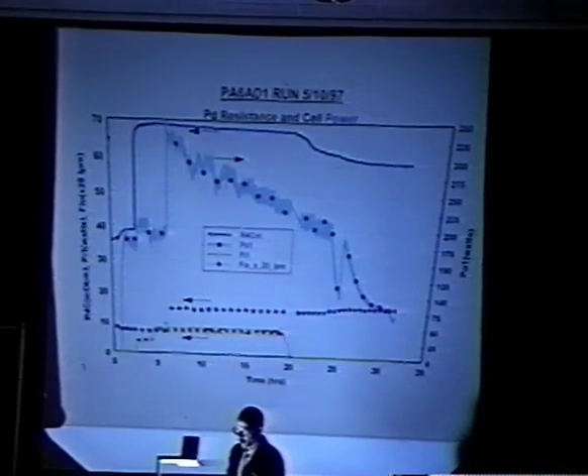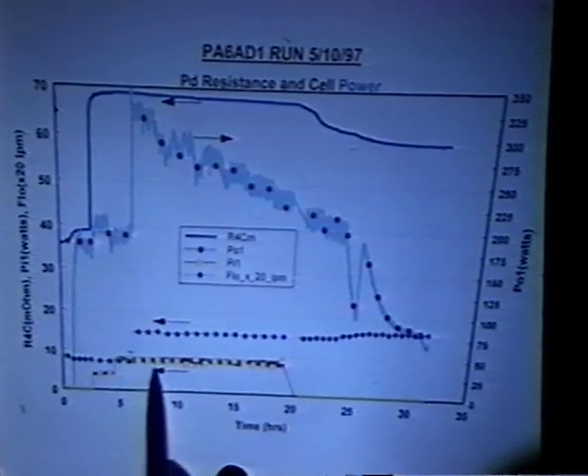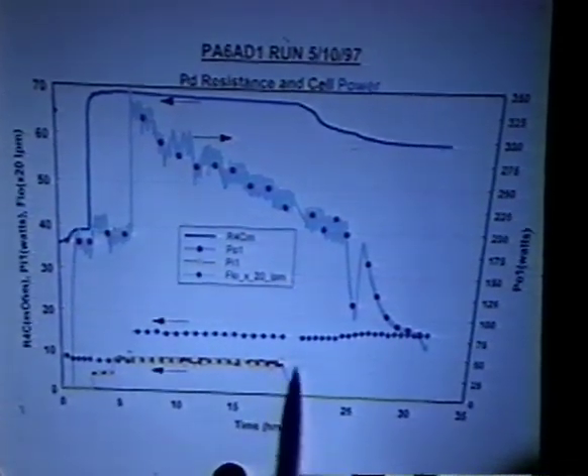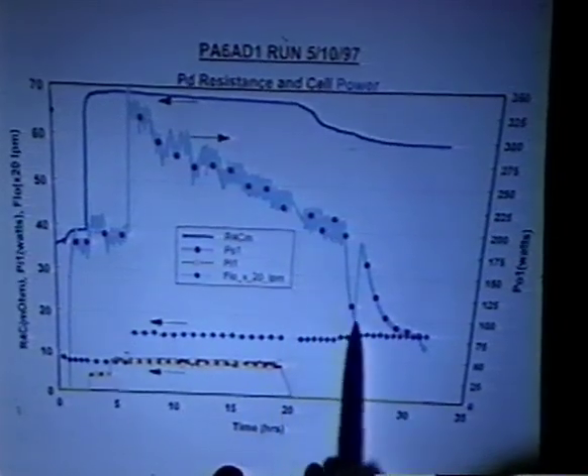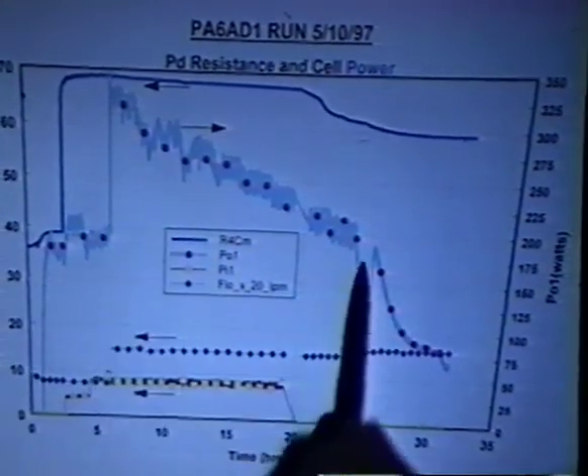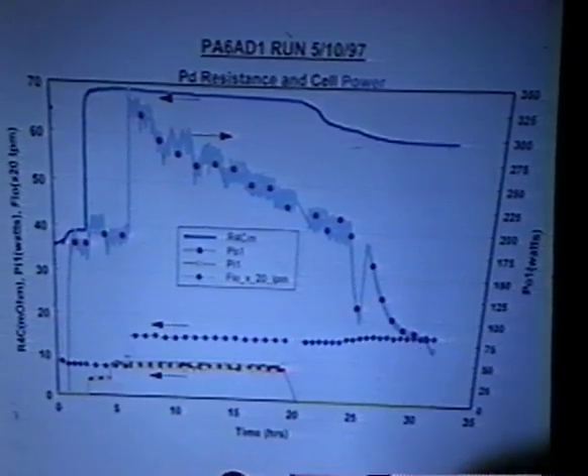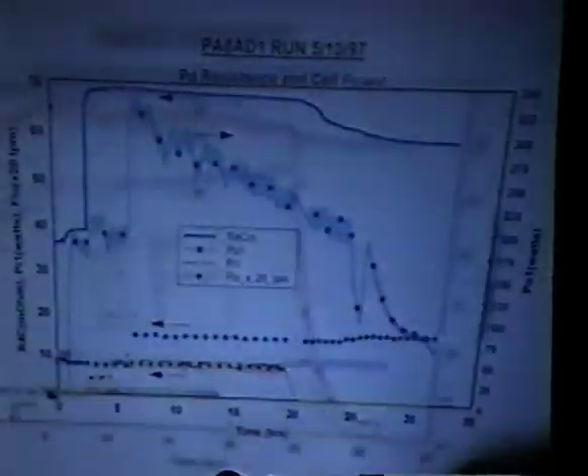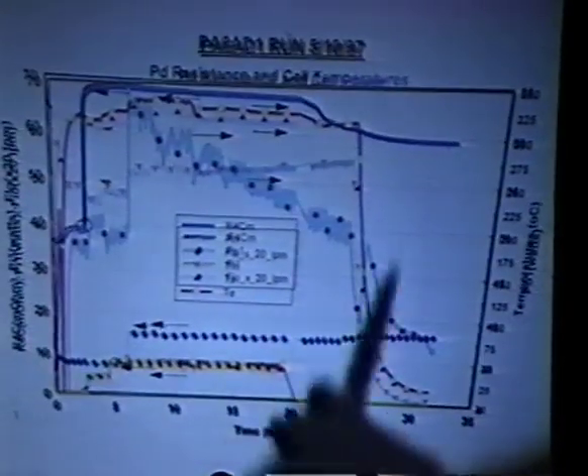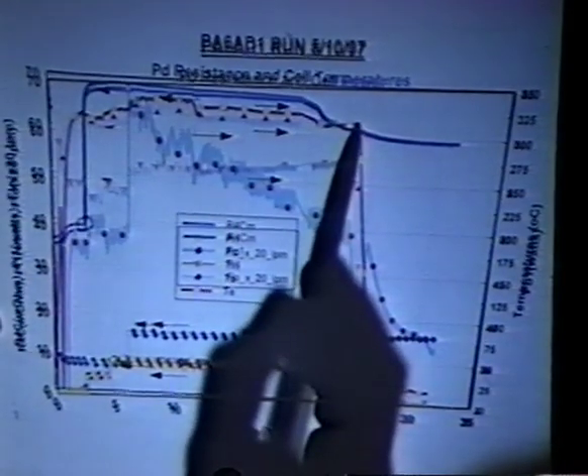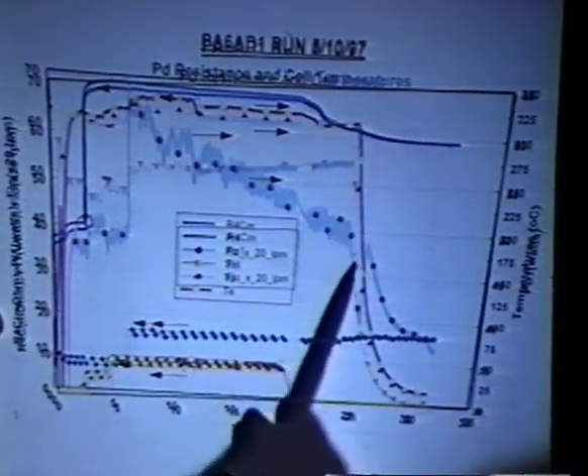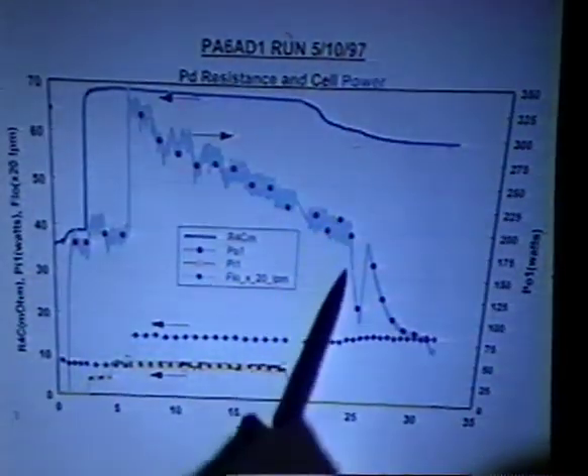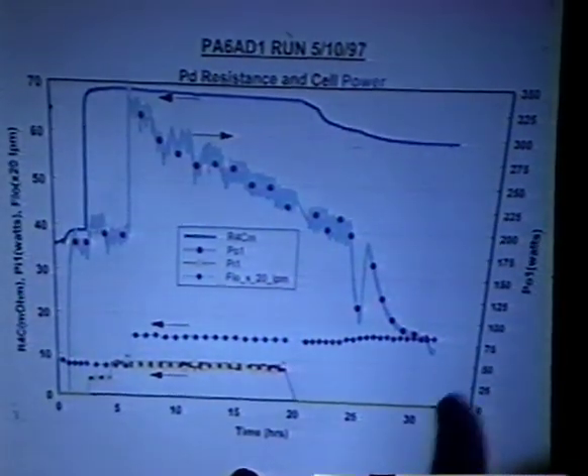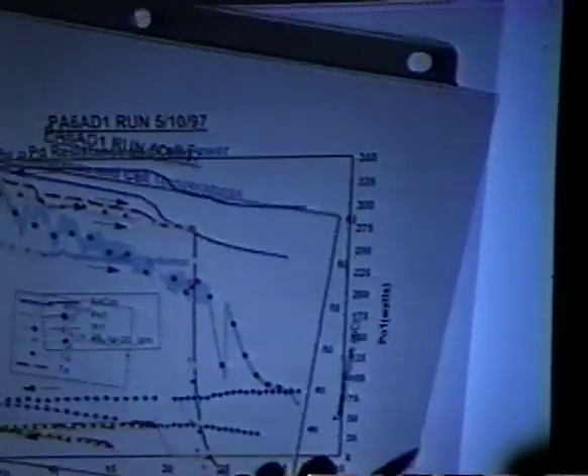And again, it varies somewhat, but somewhat independent of the current. The current's turned off here. We see a small drop in this thing over here. I'm just letting basically the temperatures come on down and cool it. In fact, you can see that if you overlay this. What I did was force cool it right here from 60 degrees centigrade, went ahead and let it come on down, and the power drops with that. So quite a bit of power shown on that.